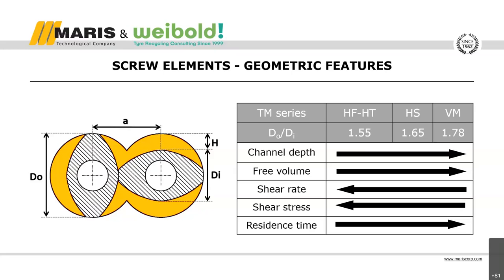As we see in the table, this ratio affects other important parameters of the extruder. Comparing the values 1.55 and 1.78, we can easily say that by increasing the Do/Di ratio, the free volume and the residence time go up, while the shear stress and the shear rate go down. In the end, depending on the material to be processed, we can offer you a different Do/Di ratio based on our know-how.